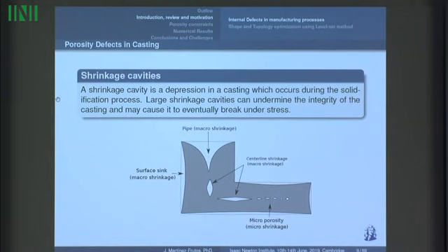The shrinkage cavities are cavities that appear due to the different density that the metal has in liquid state and in solid state. So during the cooling process, the metal retracts a little and gets more dense, leaving the hot spots of the structure without any material. This defect is very harmful because it's related with fracture and other kinds of degradations of the performance of the structure.